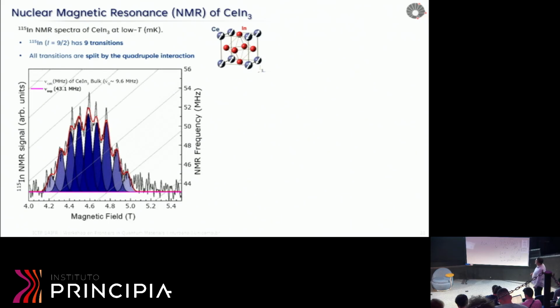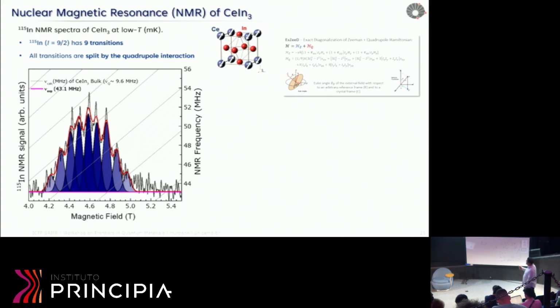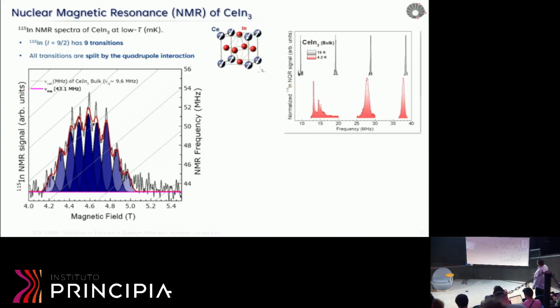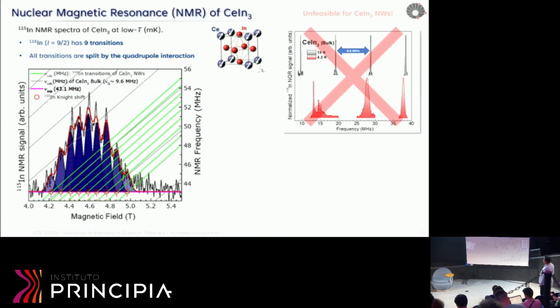To understand that, we tried to model it and calculate, doing exact diagonalization with the Hamiltonian. Well, the first guess was using the quadrupole frequency from the bulk material. As you can see here, those are the frequencies for that, and those lines do not match our spectra. So this doesn't work for our nanowires.